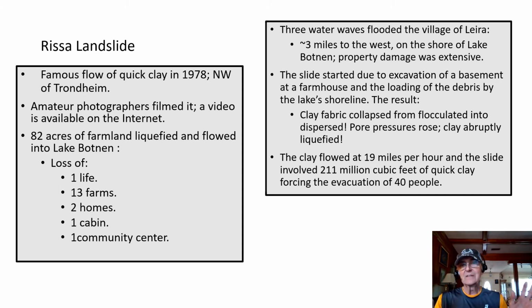Now listen to this. The slide started due to an excavation of a basement at a farmhouse and the loading of the debris by the lake shoreline. What happened? Well, the clay fabric collapsed from a flocculated into a dispersed arrangement. The pore pressures increased dramatically. The clay abruptly liquefied, flowing at a velocity of 19 miles per hour, and the slide involved more than 211 million cubic feet of quick clay, forcing 40 people to be evacuated.